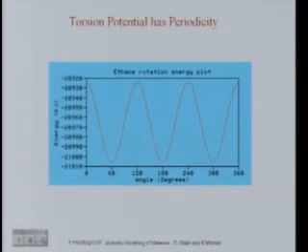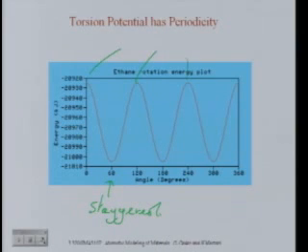And here's the ethane rotation energy plot. So what you see is that it's minimal at 60 degrees. This is the staggered configuration. And this is 120 and 0 and 240. These are the eclipsed configurations. And so these are easy potentials to make because all you have to look at is what the symmetry is of your torsional states. Okay. So if for some reason it's 90 degrees, you'd usually have a cosine of 4 omega. Okay. If it's 180 degrees, you'd have a cosine of 2 omega.